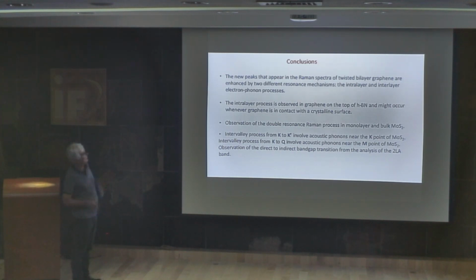Then the specific conclusions: the new peaks that appear in the spectra of twisted bilayer graphene are enhanced by 2 different mechanisms, the intralayer and the interlayer electron-phonon process. In one case everything occurs in 1 layer, in the other case there are electrons from different layers. The intralayer process is observed also when I have graphene on top of HBN, and might occur whenever graphene is in contact with a crystalline surface.